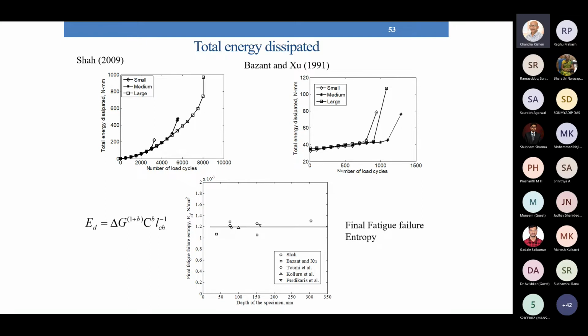That means this energy which is dissipated does not depend on the size of the specimen, and we also see the same behavior for a different concrete mix. And the entropy at final failure we have plotted here, and for any size, the depth of the specimen is plotted on the horizontal axis. This we see almost remains constant. Again, this final fatigue failure entropy can be used as a material parameter, or it can be used as a failure criterion to determine the number of cycles it takes to dissipate this amount of energy. So it can be used as a failure criterion.